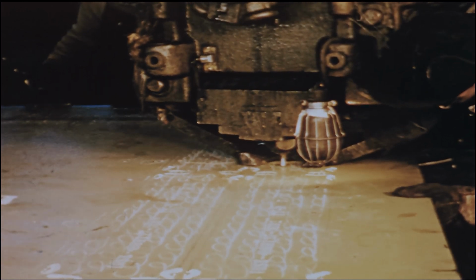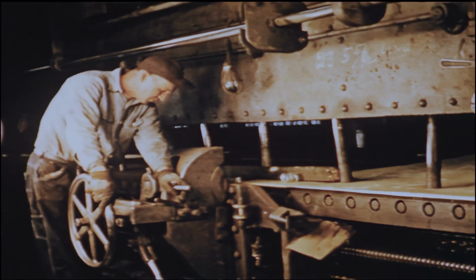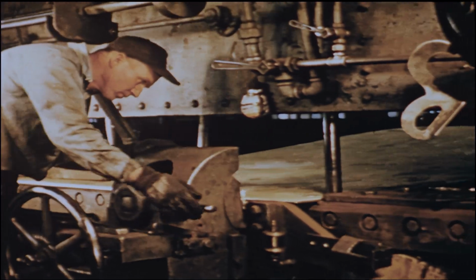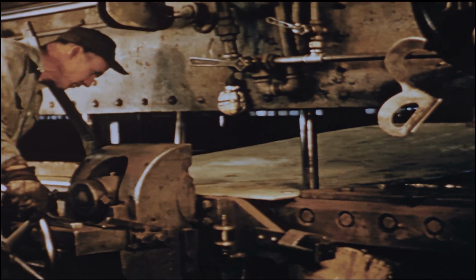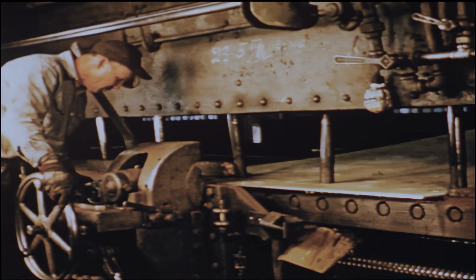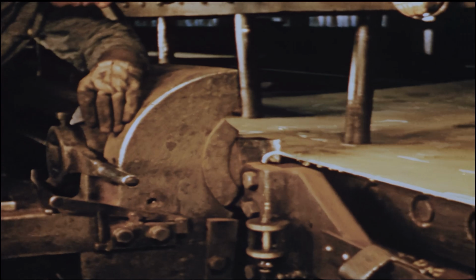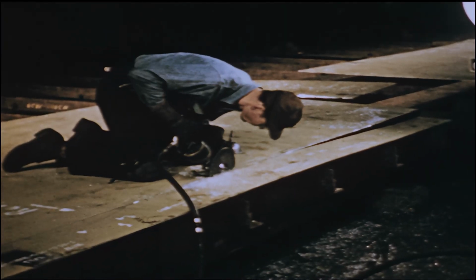Care must be taken in the handling of aluminum, as it mars easily, making dents and buckles difficult to remove and preserve the fair surface. The boundaries of large aluminum plates laid off to the full size of the material are planed square to the line. Odd-shaped plates, which do not utilize the entire plate area, are sawn to shape, whereas with steel, such operations would normally be accomplished by burning.